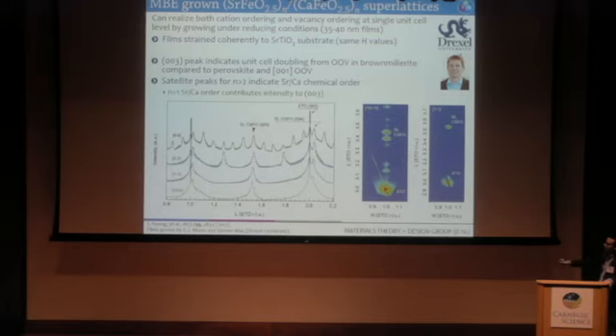For all of these superlattices, you see the additional Bragg reflection from the brownmillerite structure. This occurs at the 003 peak. And then these added satellite features are indicative of chemical order, 2,2 chemical order, 6,6 chemical order. The complication is that for the ultra-short period superlattice, the 1,1, the chemical order leads to intensities at the same Bragg reflection that gives rise to the brownmillerite structure. So it's buried in this reflection.